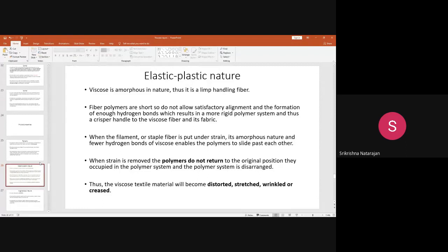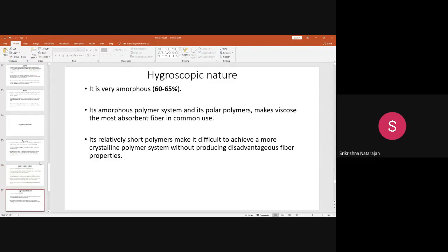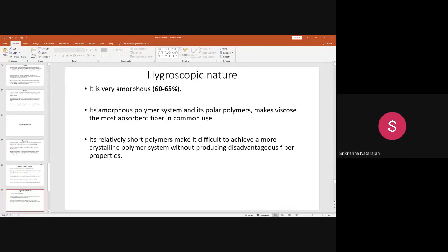Next, chemical properties. It is a highly amorphous fiber — 60 to 65 percent amorphous — so it is a very polar kind of polymer that is highly water absorbing. These fibers are used as super absorbent fibers. You may have heard the term SAF — super absorbent fibers — which have high absorption. Wherever high absorption is required these fibers can be used because they are highly hygroscopic. The polymer system is 60 to 65 percent amorphous and 30 to 35 percent crystalline — one third crystalline and two thirds amorphous.